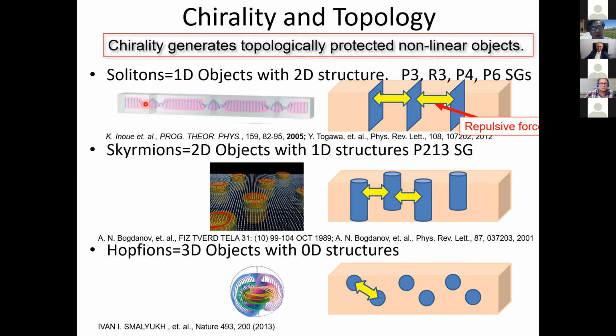If we consider a monoaxial or uniaxial chiral magnet, it can generate a one-dimensional soliton like this. But if we make a 2-dimensional object in a chiral magnet, we can make a skyrmion state. But a higher, three-dimensional object is also mathematically possible. This is the so-called Hopfion. Hopfion was very recently found by Ivan Smalyukh in a chiral liquid crystal phase. But nobody has found it in a magnetic system.